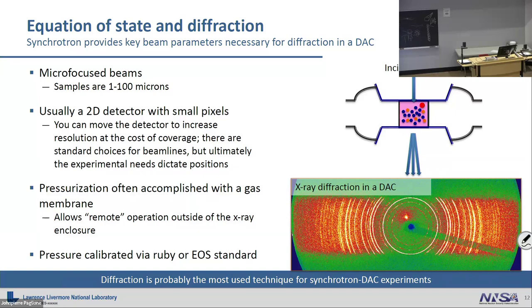One of the last experiments I did, which was a long time ago now, at the beam line, I think I took an entire pressure run in about an hour. I set it to go remotely and I walked away and went to lunch and just took the data while I was at lunch. Every exposure was like half a second. So just the way the focusing has gotten and how much flux you can get out of it and how good the monochromators are, you can really burn through some diffraction patterns in terms of getting the data. It takes you much longer to analyze everything.